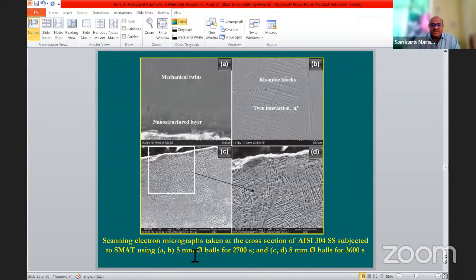So when we impinge the substrate material, the stainless steel material, with the 5 mm dia steel balls for about 2,700 seconds, automatically you develop a nanostructure layer on the surface. And there will be mechanical twins induced in the microstructures. There will be formation of rhombic blocks and twin interactions, the formation of alpha prime martensite. So you can see these things.